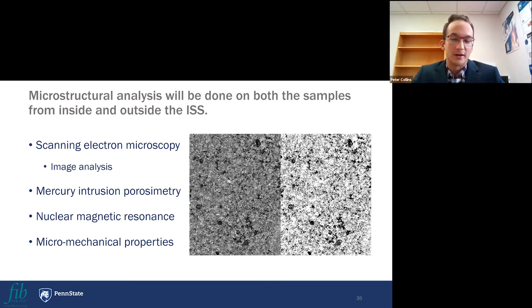And while our samples are quite small, of course, they're not normal cylinders by any means, and they lack a definite shape half the time. So we can't do our traditional mechanical testing like compressive strength and all of that. So we're going to look at the micromechanical properties through indentation techniques such as nano indentation and micro hardness testing. And this will give us an idea of whether there's any micromechanical differences between the two samples that were left here on Earth and the ones that were done on the ISS.